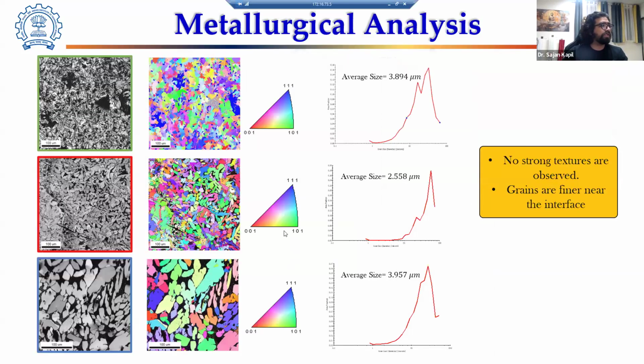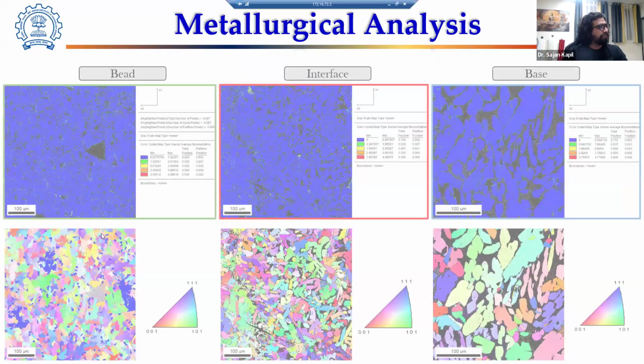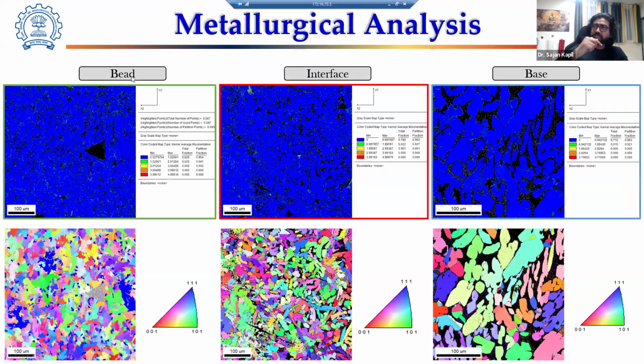As well, we performed texture analysis, and the EBSD texture shows quite random colors here. That means the orientation is quite mixed, not biased in any direction. Okay, we observed it on the bead. Bead, when I say it, is the deposited part, at the interface and at the base. And of course, the base looks different. The reason is obvious, because it's a casted part, right? I mean, the base is casted.